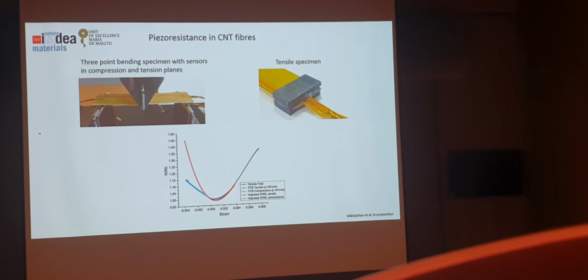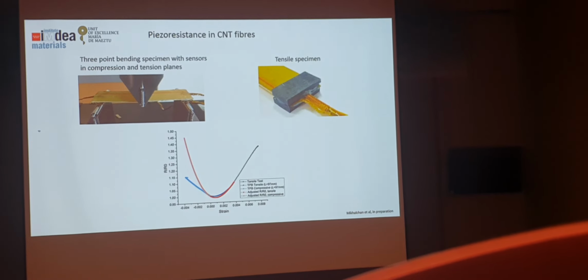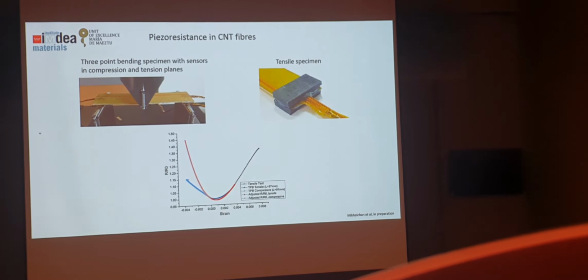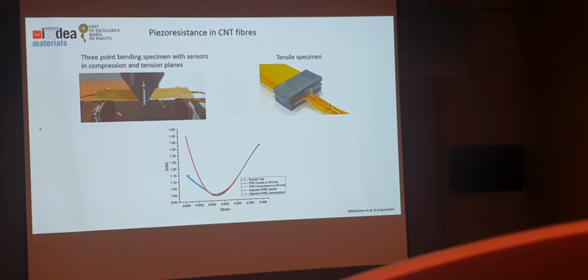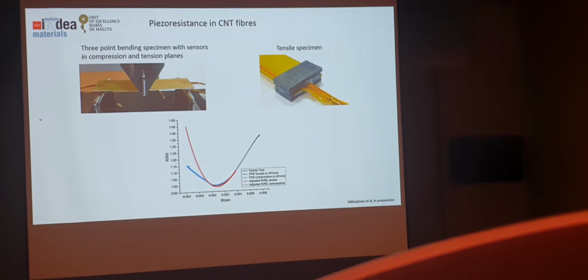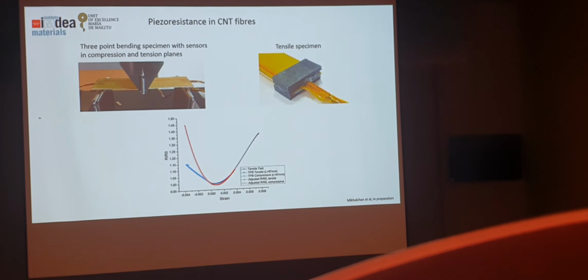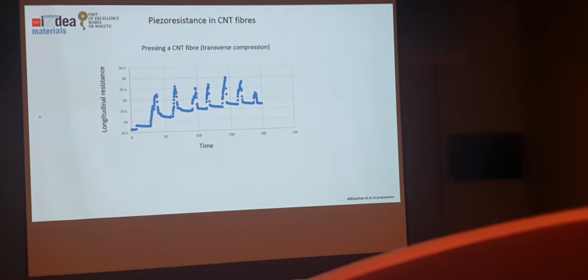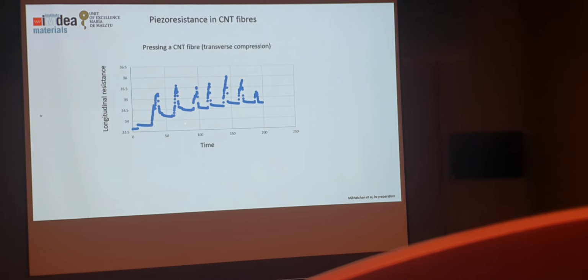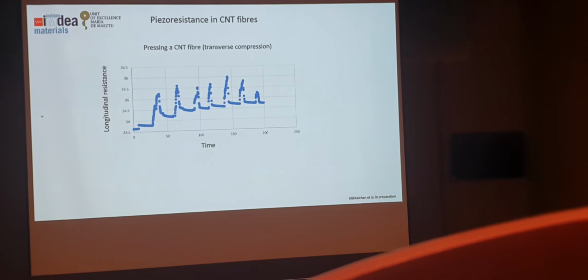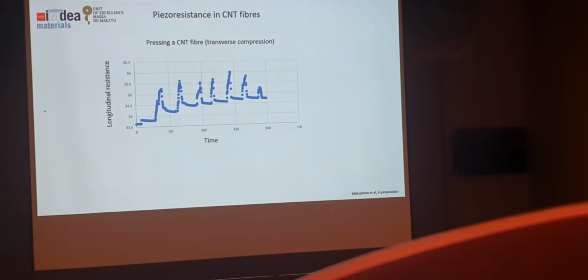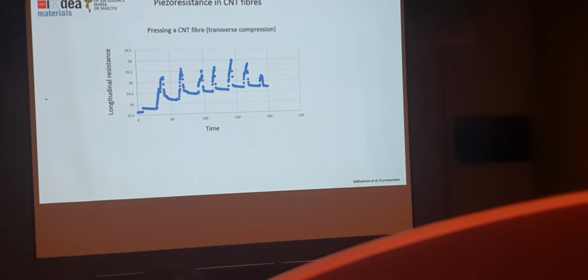And we see this U-shape consistently. So in other words, whether you compress the fiber or you stretch it, you still get a positive piezoresistance. So I asked my student, well, go and tap on the sample and see if you compress it transversely, right? So you go and press it with your finger, well, not your finger because you make it warm, but press it with something, and you also get a positive coefficient. So the piezoresistive coefficient is positive irrespective of the deformation.